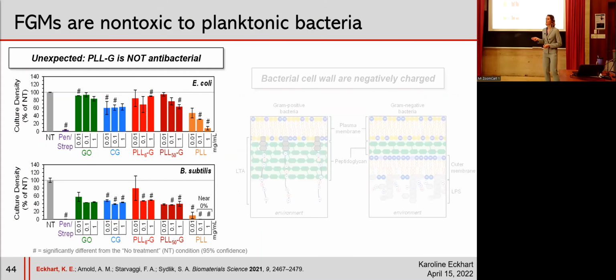We next wanted to evaluate how these FGMs interact with bacterial cells. Understandably, the GO and the clay and graphene were well tolerated by both gram-negative and gram-positive bacteria. This has been reported widely in the literature, and so this was an expected result. But shockingly, the PLLG was actually also compatible with bacteria. It did not cause a significant decrease in the culture density of the bacteria.